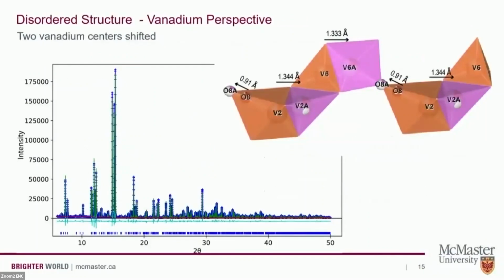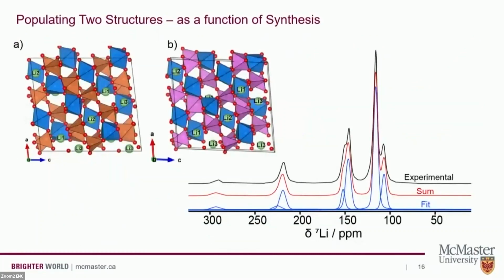So Tiana searched through the sample, found a single crystal, and was able to do a diffraction experiment at our facility at McMaster. And what they determined was there's a small amount of twinning in the structure. So 15% of the vanadium-2 and the vanadium-6 move slightly in their crystallographic positions and occupy 85% the orange sites and 15% the pink sites in the structure. So that gives us 2 different ways for the local environment to contribute electron density from the vanadium into the lithium sites. And so now we wanted to think about deconvoluting this spectra as a set of 2 sets of 3, like I mentioned. So we have 2 parent structures.